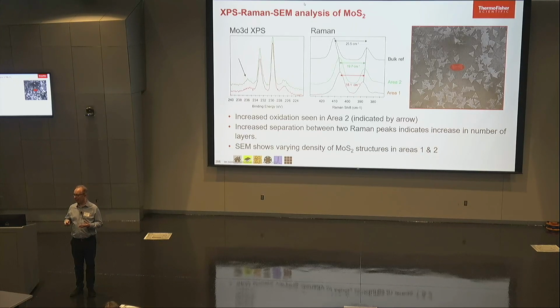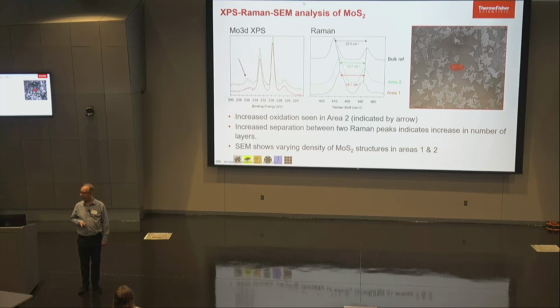Because, you're quite right. We don't want to gold coat samples if we're going to do XPS on them. We don't want to carbon coat them. The usual way that you would make insulating samples conductive for doing SEM on is exactly what you wouldn't want to do if you want to do surface analysis on them, because putting a carbon coating down means you'll just detect carbon in the XPS. Gold coating, just detect gold. So you have to use the low vacuum mode of the SEM. So you do need an environmental SEM if you're going to look at insulating samples.